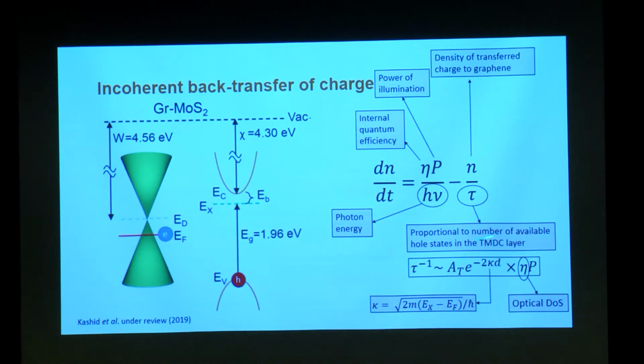This rate is essentially proportional to the number of available exciton states or hole states in the chalcogen layer. And that has two aspects. One is it is directly proportional to the optical density of states in the chalcogen layer and the energy difference between the Fermi energy and the excitonic state energy. So these two parameters will determine the speed at which the electron can be back transferred into the chalcogen layer. But very importantly, these are incoherent tunneling events, and hence this can be exponentially long. This can be in the orders of seconds that we have seen in the